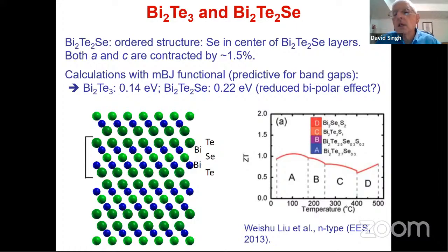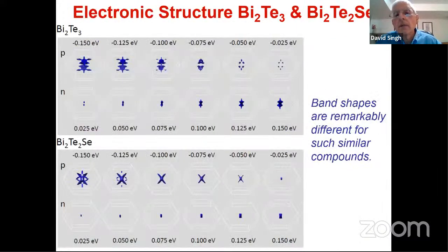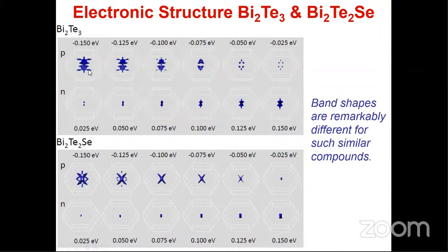So we decided to make some calculations, but we didn't obtain what we expected. I showed you those isosurfaces for lead telluride, perhaps you remember. Now I just want you to focus on these two. This is bismuth telluride, and this is bismuth telluride with selenium. You can see these isosurfaces are quite complicated. In other words, they're not spheres. A parabolic band would give you spheres. But it's not.